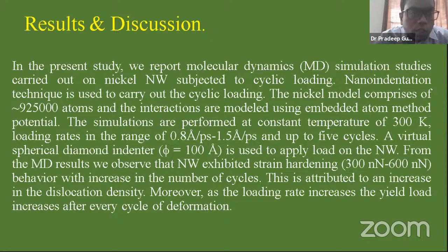In the present study, we report molecular dynamics (MD) simulation studies carried out on nickel nanowires subjected to cyclic loading. The nanoindentation technique is used to carry out the cyclic loading here. The nickel model comprises around 925,000 atoms, and interactions are modeled using embedded atom method potentials. The simulations are performed at a constant temperature of 300 Kelvin, and the loading rate ranges from 0.8 angstrom per picosecond to 1.5 angstrom per picosecond, up to 5 cycles here.